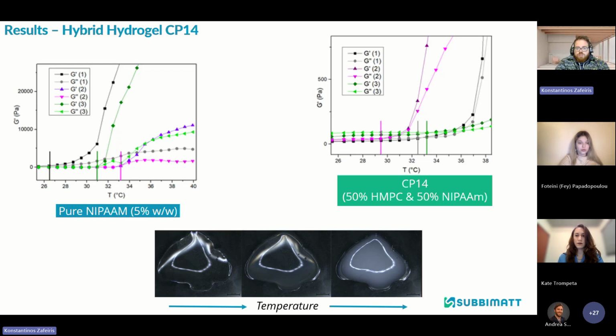And we also, for comparison, tested the pure synthetic polymer to be sure about the transition, and we can see that it is happening in a similar region, which confirms that it has a really critical role in our hybrid system. The slight variation that someone can notice in the transition temperatures in the hybrid formulation can probably be attributed to factors such as the inhomogeneity of the sample or some thermal gradients during the measurement itself. So overall, this system successfully shifts the thermoresponsive behavior into our application range.